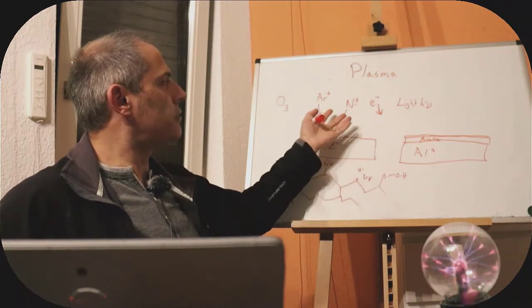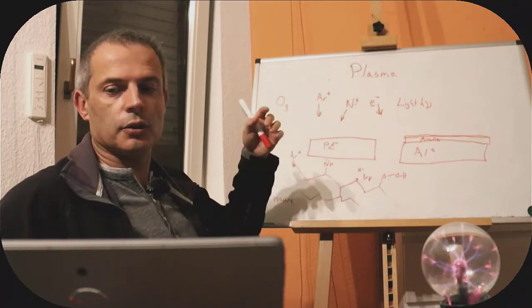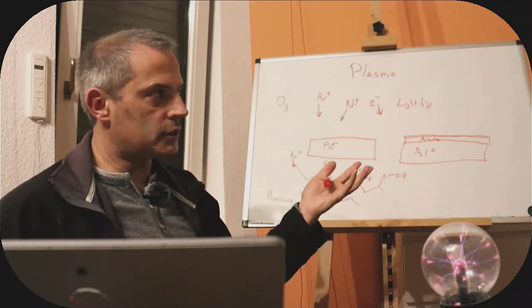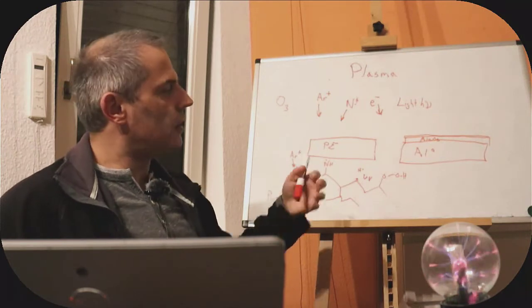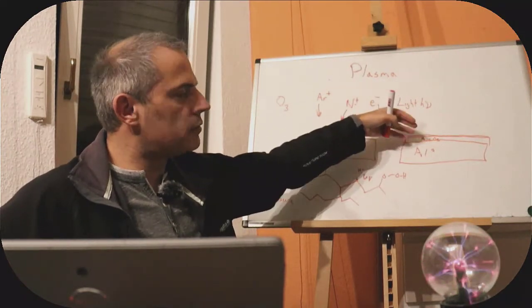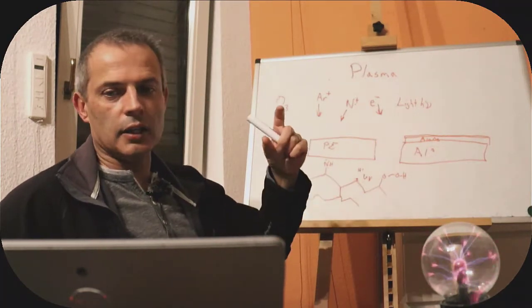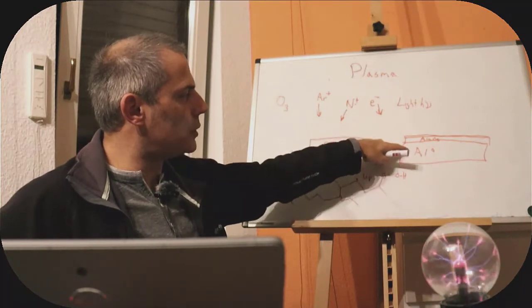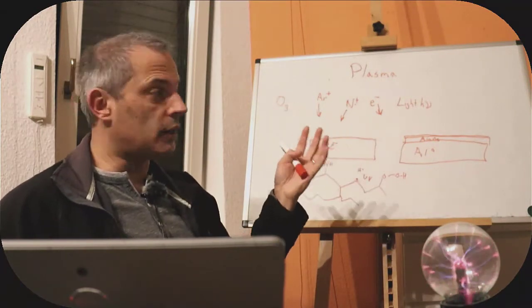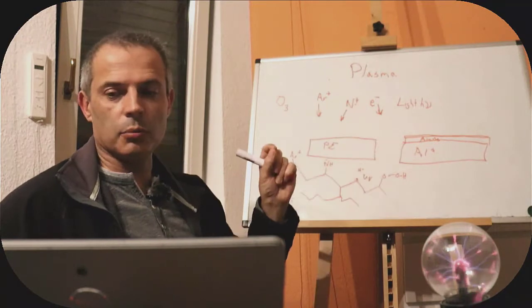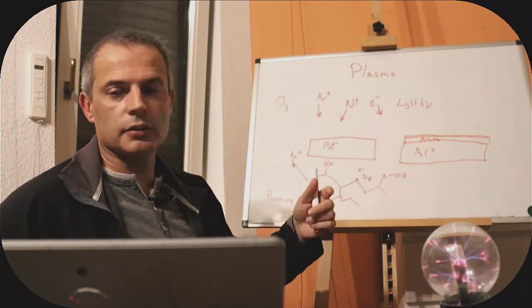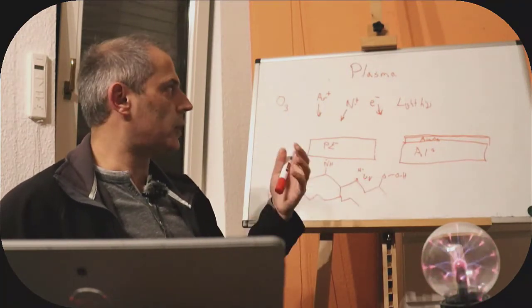But if we have these species, particularly ozone and O2 minus, the oxygen anion, whacking into our aluminium surface, that will cause a larger voltage to appear between the aluminium and the outside, like we had last time, and that will cause our aluminium oxide to grow in thickness, but in a different way than we had before.